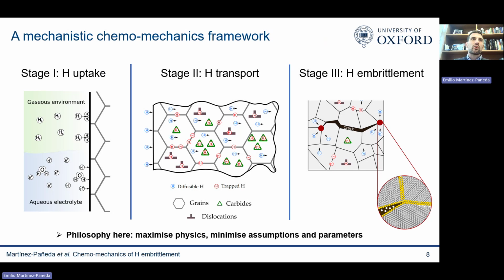a mechanistic computational model capable of predicting when hydrogen-assisted failures will happen. My philosophy has always been to maximize the physics and minimize assumptions and parameters. Ideally, I would like a model that does not rely on magic fitting parameters, alpha, beta, that have no physical meaning. I want a model that relies purely on well-identified physical properties I can independently measure in my lab: yield stress, diffusivity, things with a clear physical meaning.